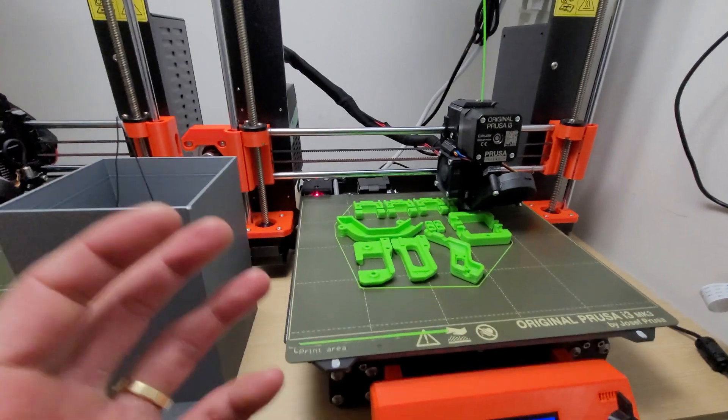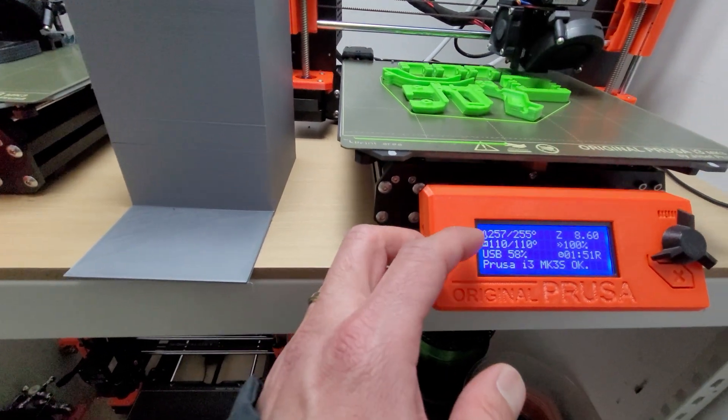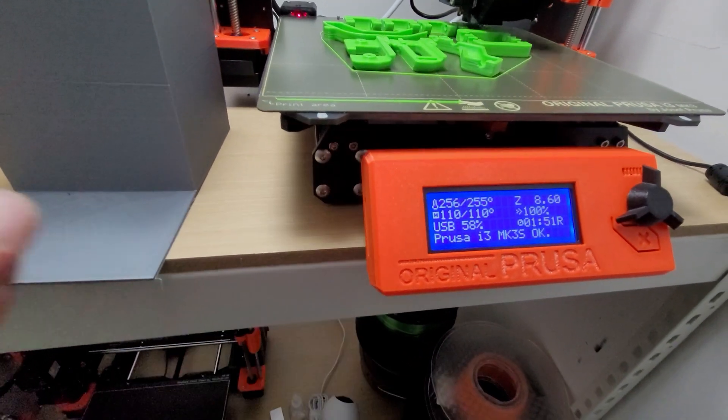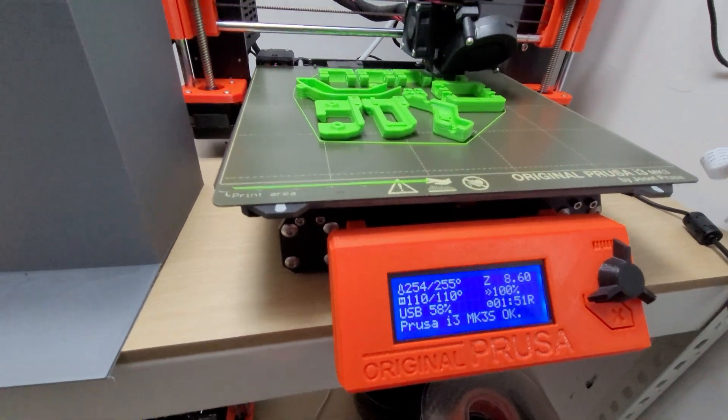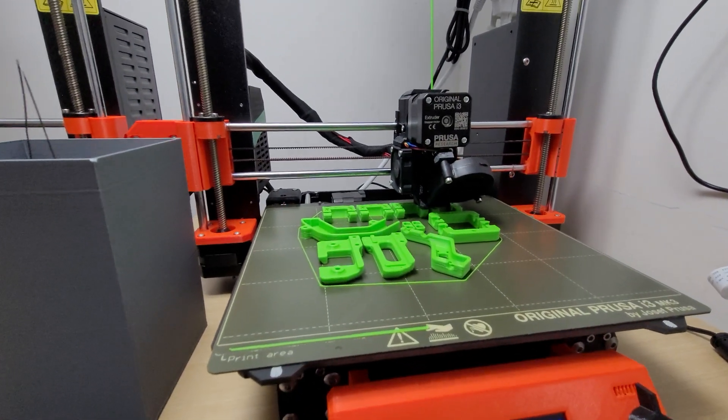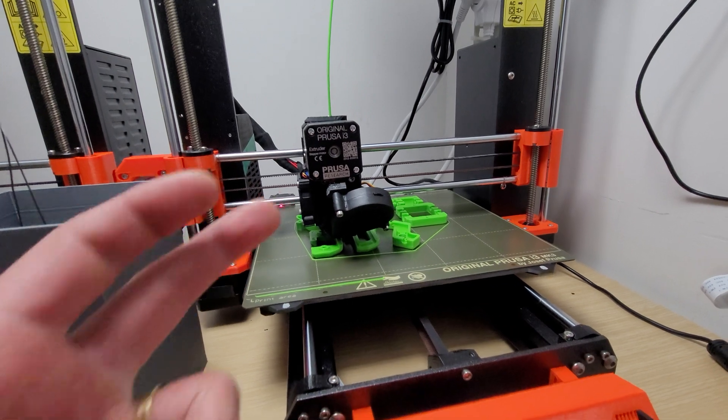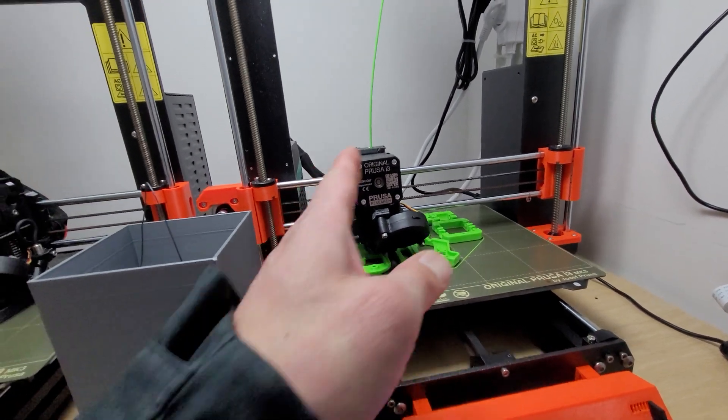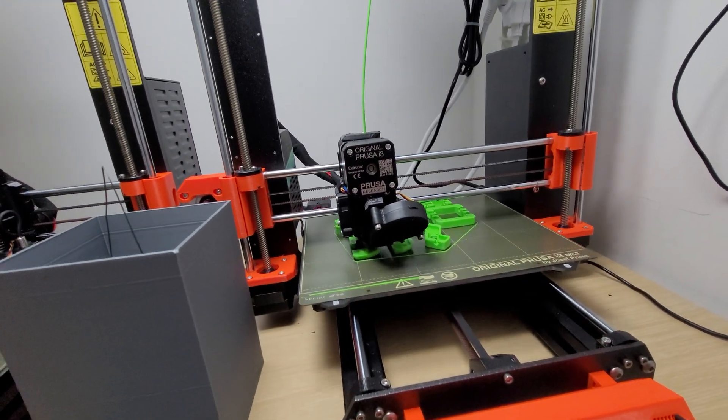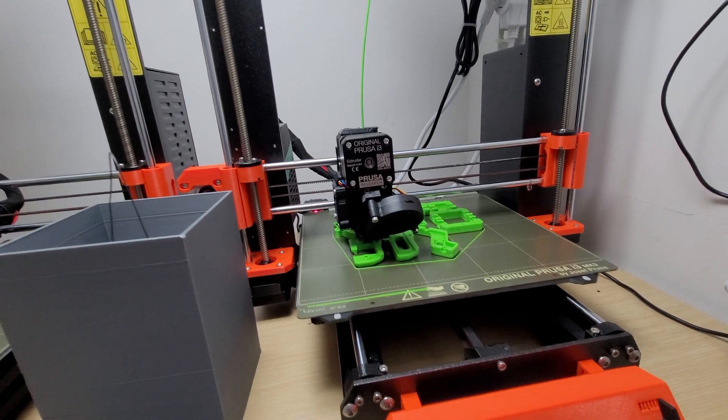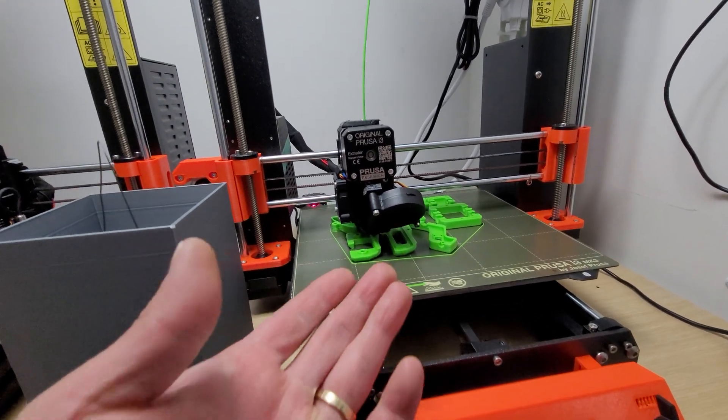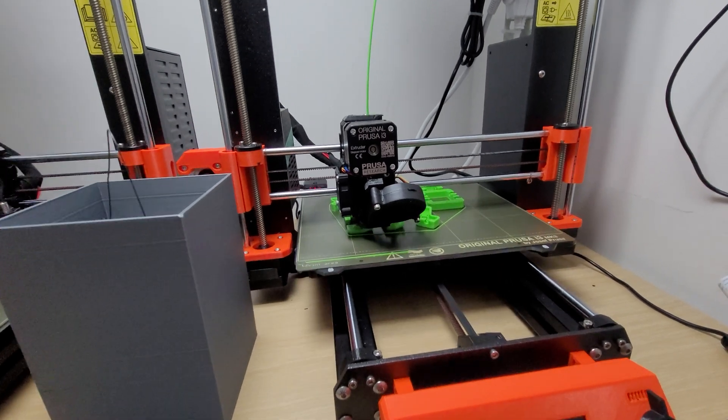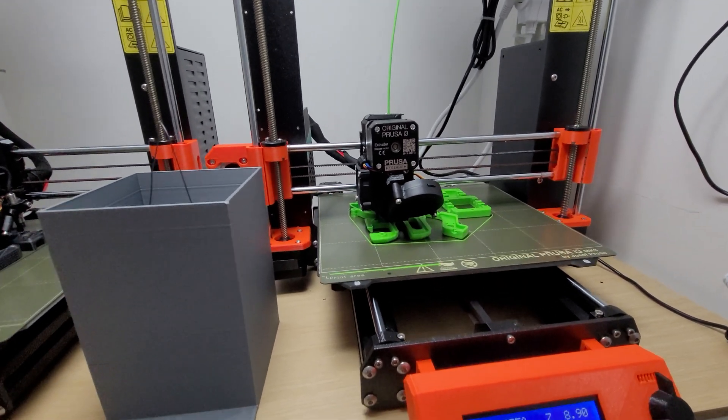Now, so how did I solve warping? I set the bed heat much much higher. I set it at 105 starting and 110 when I'm actually after the first layers. And I just put a small layer of glue stick all over. You'll have to clean it up. Just take the whole plate out. The good thing with Prusa is you got a removable plate. You can just go ahead and wash it after.